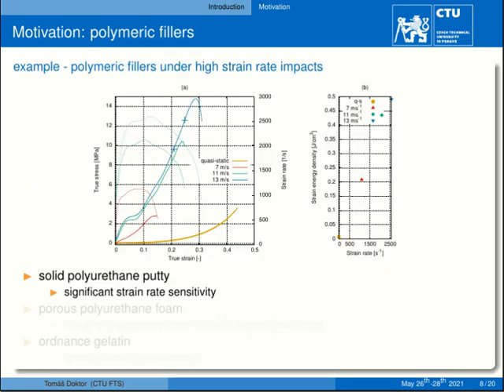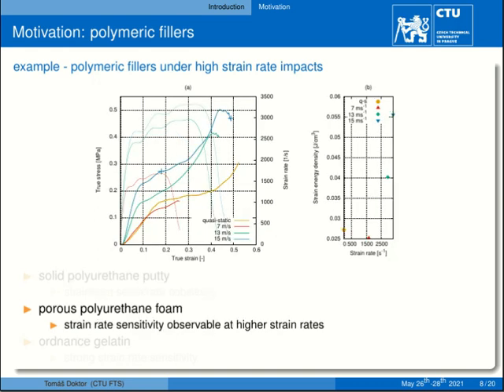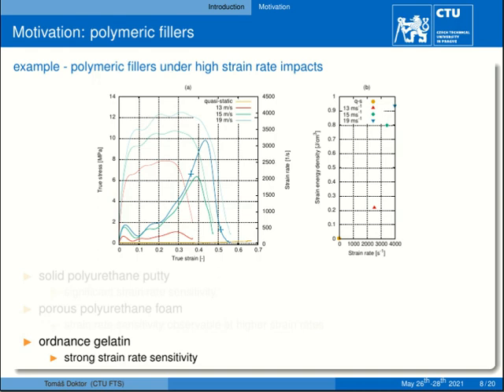The possible polymeric fillers were tested also at higher strain rates. Here you can see three representatives of such candidates to fill the open cellular structure or the open lattice to enhance the impact energy absorption properties. Here you can see significant strain rate sensitivity exhibited by polyurethane putty. On this diagram you can see porous polyurethane foam, which will be also presented in our results here. And a strong strain rate sensitivity was observed also in ordnance gelatin, which is presented also in the further results.